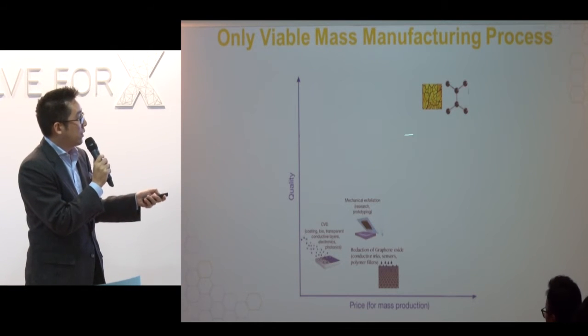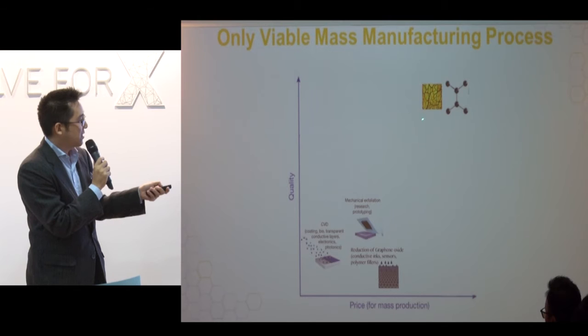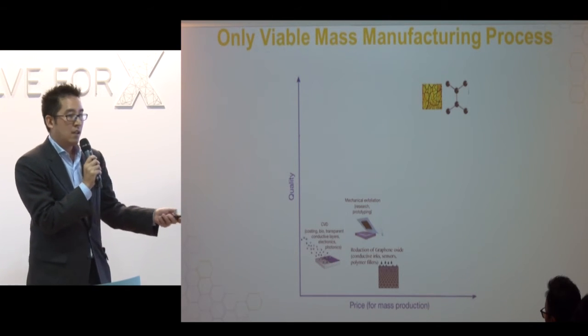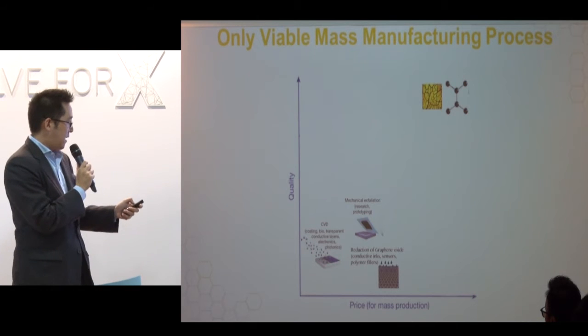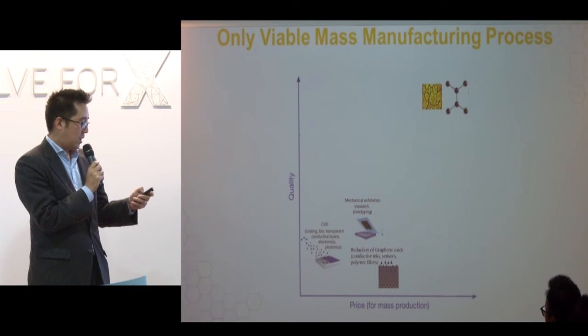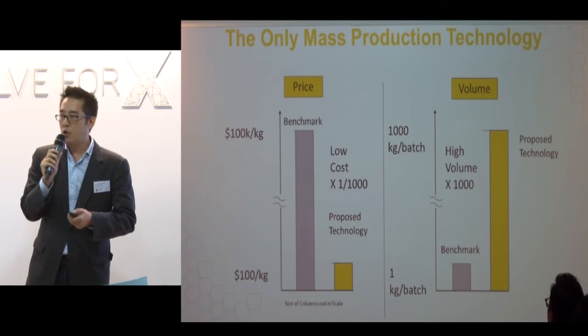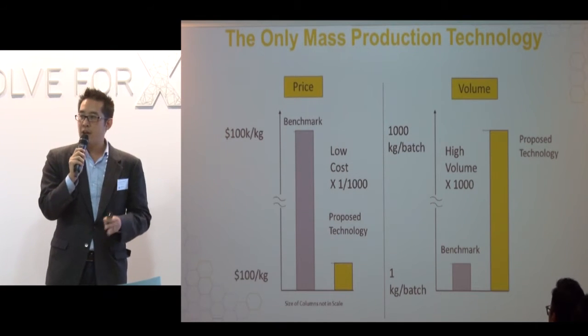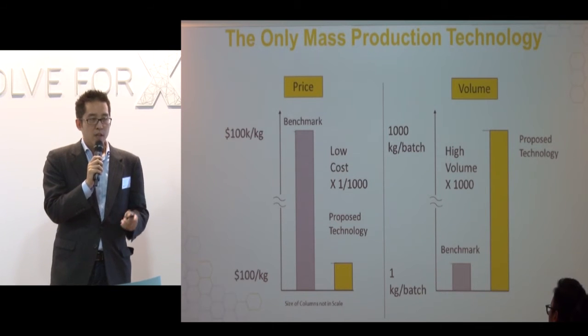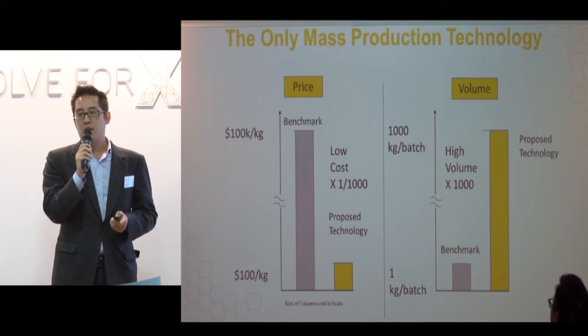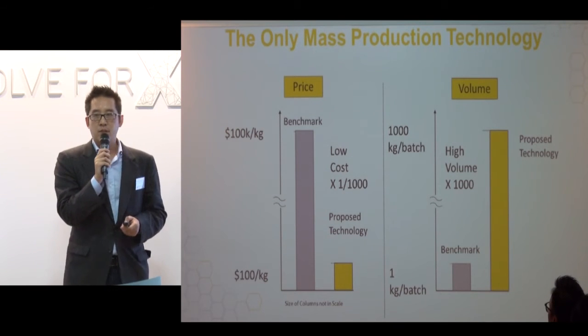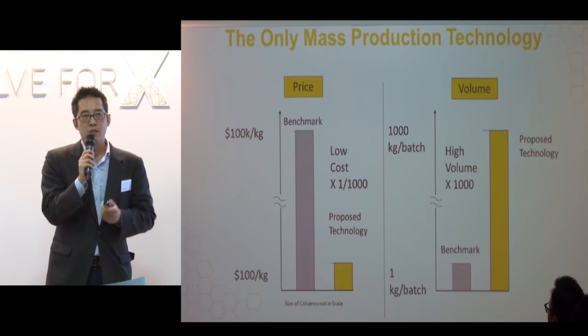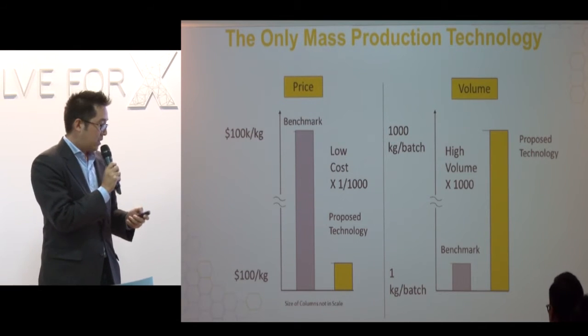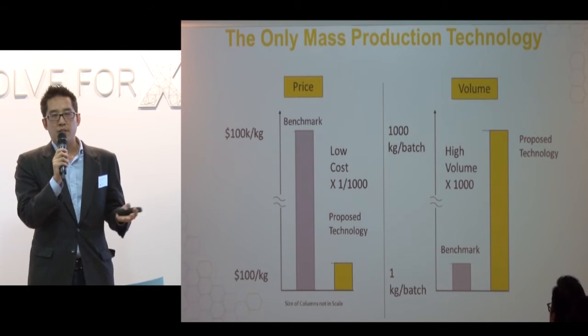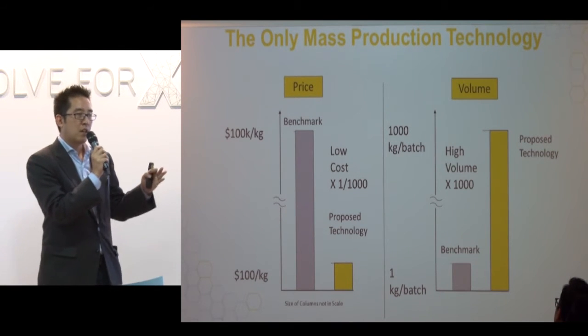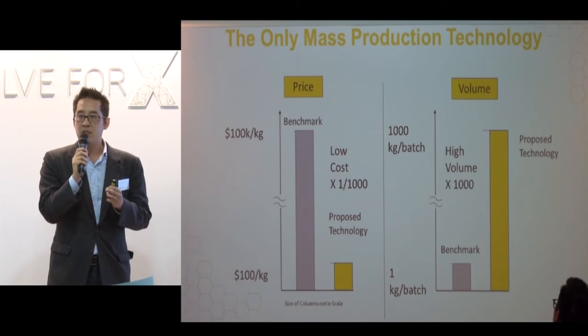We are literally the only ones in this category, for both the ability to create a very low-cost product as well as a very high-quality, high-volume product. So our goal, it might sound quite extreme, but I assure you it is actually quite reasonable, is we intend to reduce the cost of graphene by at least 1,000-fold, from $100 per gram to $100 per kilogram in the initial stage. And second, we will be able to increase the production of the graphene from kilogram scale to ton scale. And that's what's needed to drive the market.